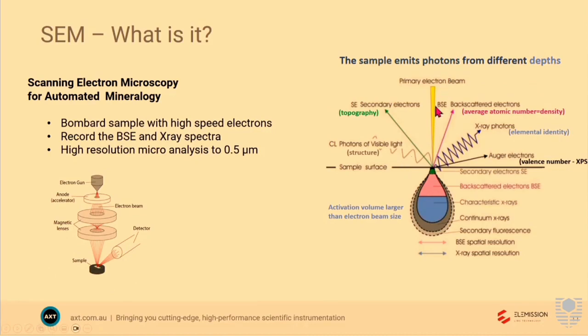When you shoot a sample with an electron beam, you get quite a few different things that come off. The original use, from what I can glean, for these scanning electron microscopes was using these secondary electrons. So it was in the realms of topography. They had better resolution, you could see a smaller particle than looking down an optical microscope. They mapped the surface of a sample. But the biggest use that we have for them is utilising the BSE electrons and the X-ray photons. You can see they all come from a slightly different depth. The secondary electrons are all very much from the surface, so they're the ones that are used for topography.